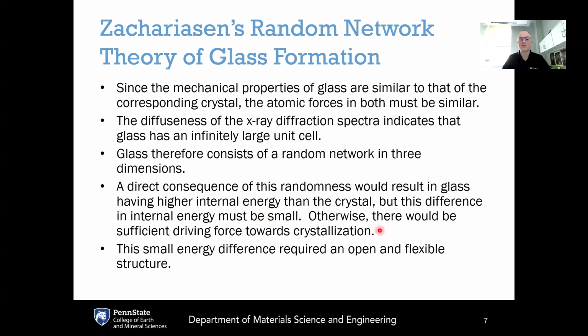Otherwise, there would be a sufficient driving force towards crystallization. In other words, glass must have a higher internal energy than the crystal, but it can't be so much higher that it becomes so unstable. Basically, that huge difference in energy between the glass and the crystal would give you a very large thermodynamic driving force, causing the glass to be highly unstable and immediately crystallize.